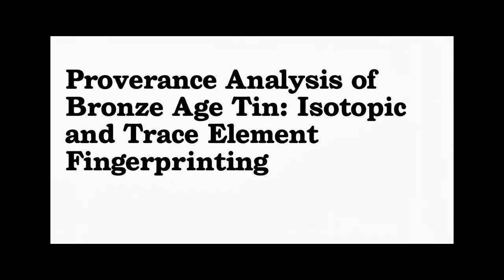So how do they actually do this? There are two main methods. First, isotopic analysis. This looks at the ratios of different isotopes of tin and lead within the ore and the artifacts. Isotopes are like different versions of the same element, just with a slightly different weight. Tin deposits formed at different times and places have unique isotopic signatures. Lead isotopes are super helpful too, because their ratios can even give a geological model age for the ore deposit, like a birth certificate for the rock.